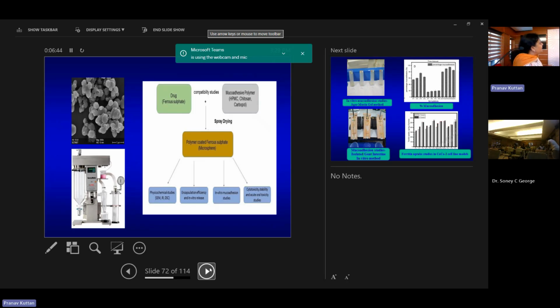So first what we did was the drug, that is the ferrous sulfate, was mixed with these different polymers in different ratios. That is the first test we do for this kind of drug delivery application. And we did compatibility studies. We will keep this mixture in a stability chamber for some 2-3 months, and we will take it out and analyze the drug. And then we will see whether, because of this polymer, there is any problem or degradation happening to the drug. If there is degradation happening to the drug, then we will not proceed with that polymer.